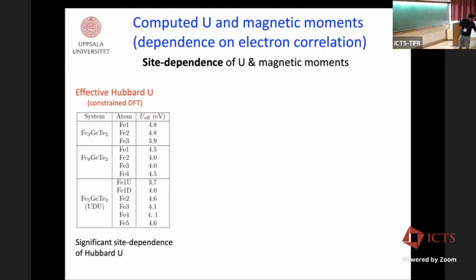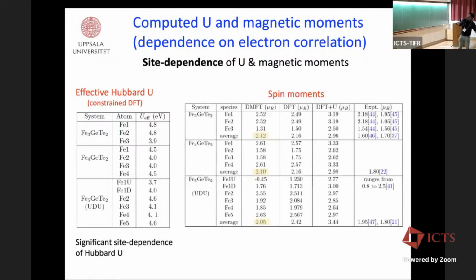If you take all these U values and calculate the spin moments, there is a comparison between DFT, DFT plus U and DMFT, and some experimental results are here. If you look into this, Fe3 germanium telluride, you see that the DMFT yields 2.12 Bohr magneton. These are all spin moments, by the way. DFT is also not bad, but the DFT plus U is actually rather large. It really does not fit with the experimental results which are given here.